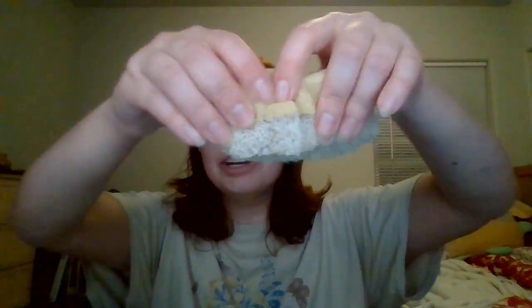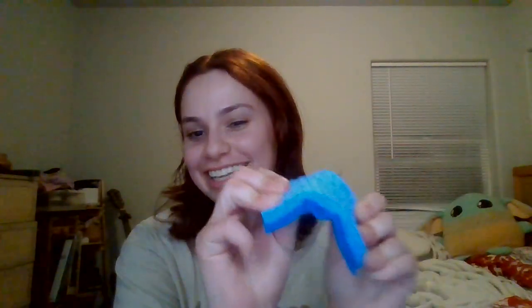When we compress a sponge, we're not compressing the entire block. We're bending thousands of little pieces of the cellular walls that deform and come back up, and they make up the skeleton of the foam. At low strains, the struts elastically bend and store energy, which is why a really good quality sponge can avoid permanent deformation. The good elastic recovery prevents a sponge from permanently flattening, like the one that we see here. This has pretty much been used forever and has reached the end of its life.